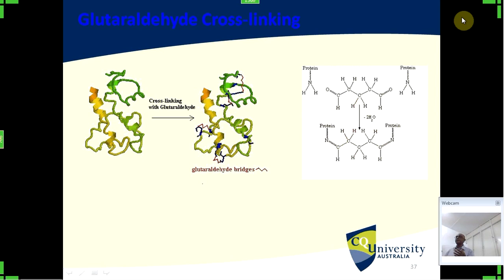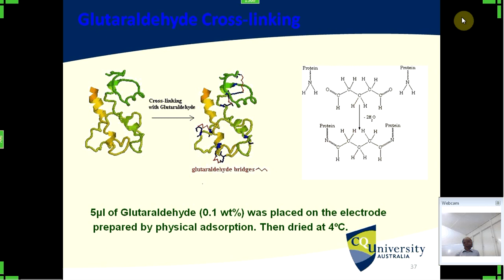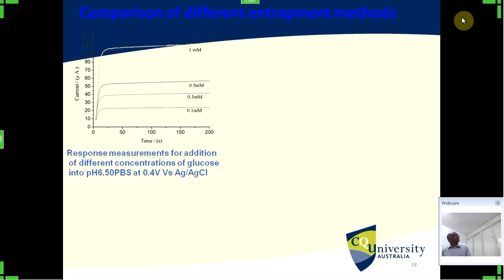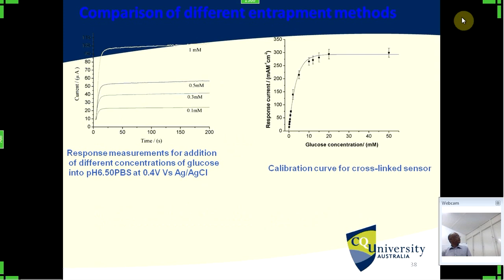And see what the other people have used for other enzymes and all. And we found glutaraldehyde is the best cross-linking agent. And applying that, 5 microliter of glutaraldehyde, 0.1 wt% was placed on the electrode in the physical adsorption and then dried at 4 degrees centigrade. And this is a curve we got after that.